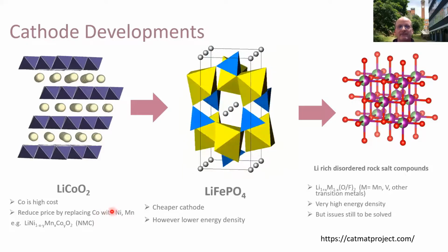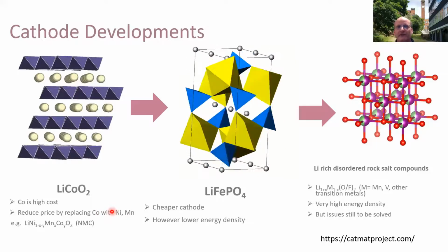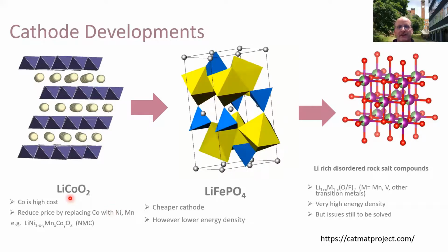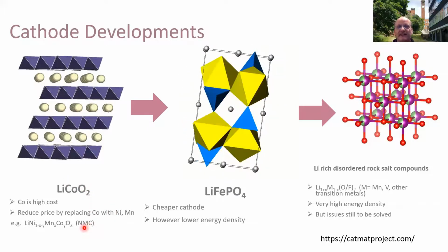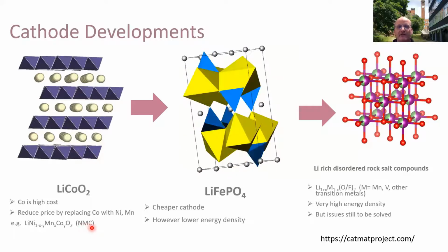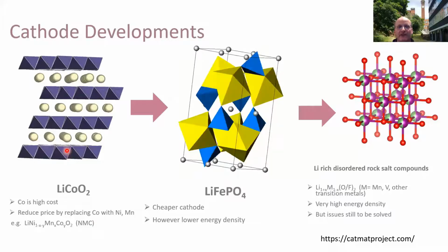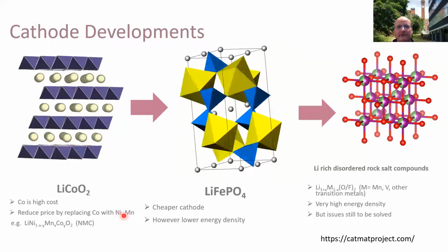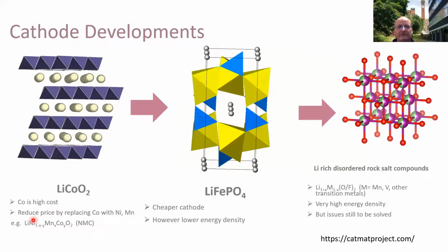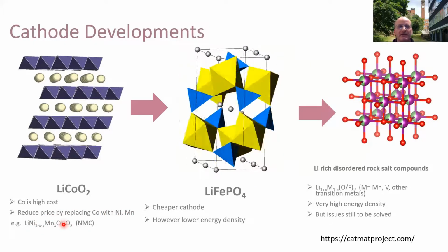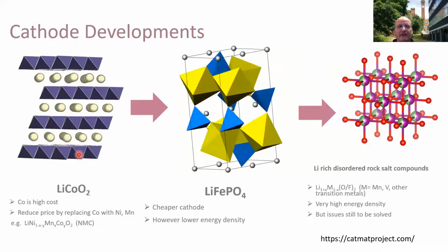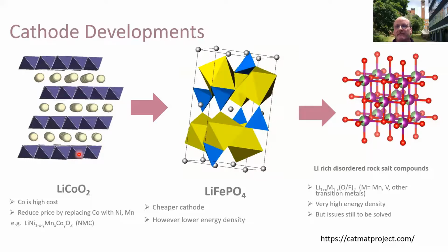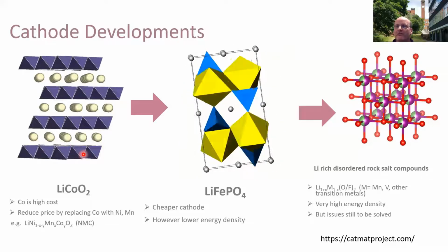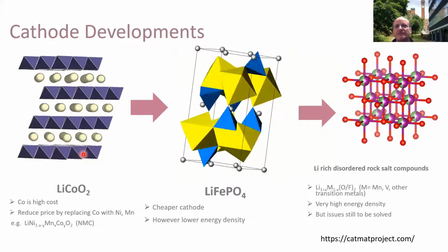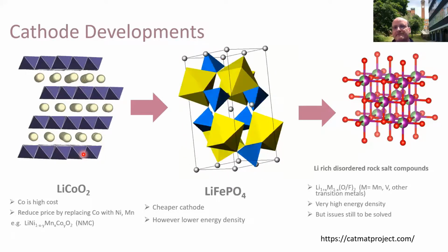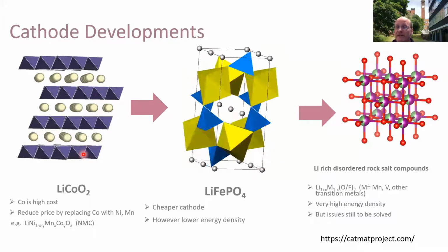And so at the moment, most of the batteries in your phone and in cars, rather than being this lithium cobalt oxide, will be this so-called NMC material. It stands for nickel, manganese, cobalt. What we've done is replaced a lot of the cobalt by nickel and manganese. In some of the current cars, you're probably talking about between 20% to 10% of these metal sites being cobalt. So we've gone from 100% cobalt to 20 to 10%. And there's a lot of interest in trying to eliminate cobalt altogether.